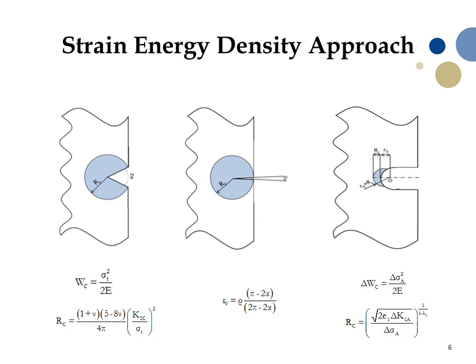The criterion, formulated by Lazzarin and Zambardi in 2001, states that failure occurs when the strain energy — or the strain energy range for fatigue loading — averaged over a circular control volume of radius RC surrounding a crack or a notch tip, reaches its critical value WC, or its critical range ΔWC if fatigue is considered.